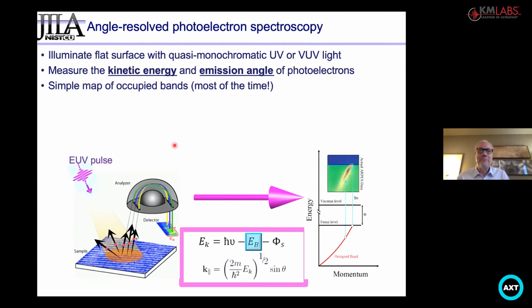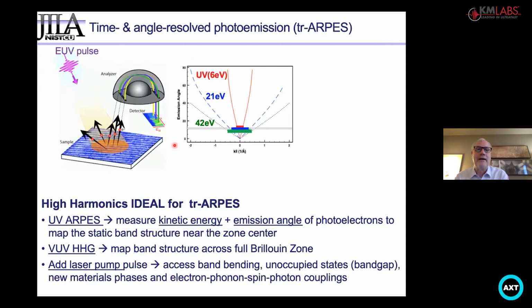And this is very simple, but some of the considerations that you have to be cognizant of are, for example, the wavelength or the energy of the photons that you're using for photoemission do constrain the photoelectrons that you can see. In other words, you actually need an energy exceeding the work function in the direction perpendicular to the surface to get the electron out.